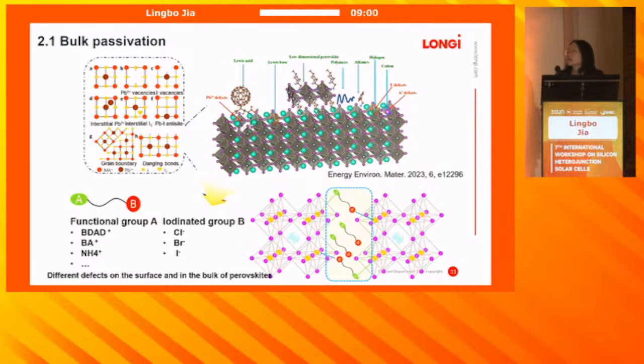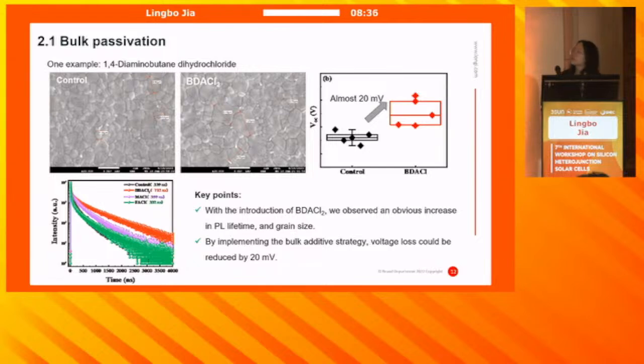First, I will talk about the bulk passivation. As we know, polycrystalline perovskite films contain different types of defects, no matter at the grain boundaries or on the surface. Here, we choose bifunctional molecules to passivate defects, which contain a functional group A and another functional group B. For example, we used BDA chloride to passivate defects. From the SEM and PL measurements, this additive can enlarge the grain size and also enhance the lifetime of perovskite films. So, by implementing the bulk additive strategy using this additive, we achieved enhanced device performance and reduced VOC loss of 20 millivolts.